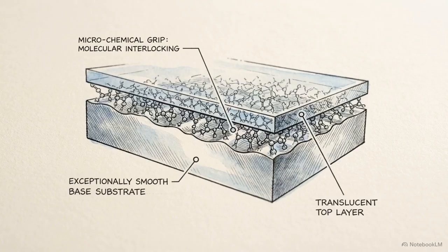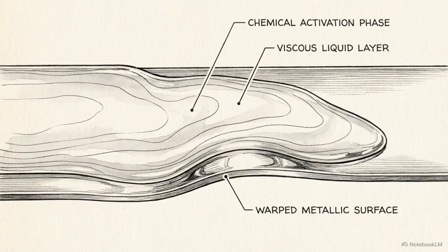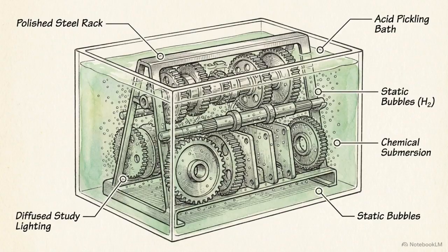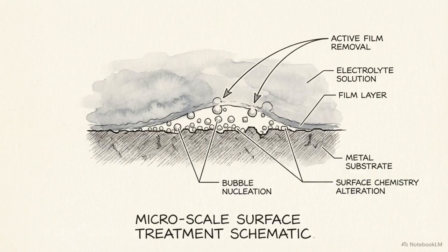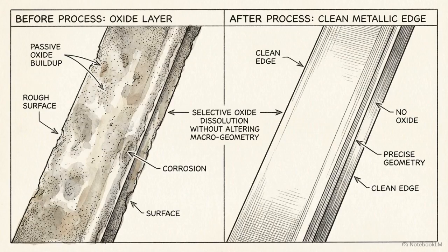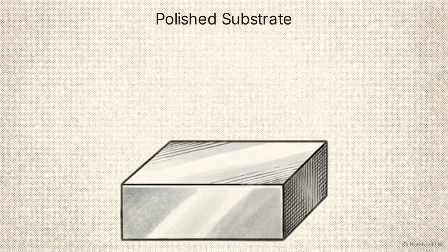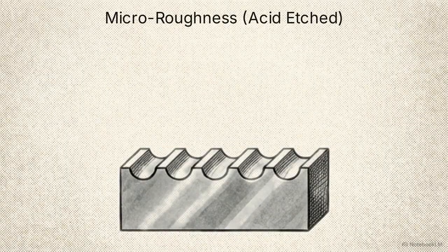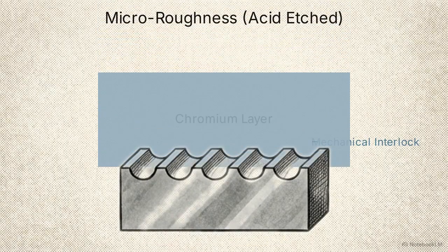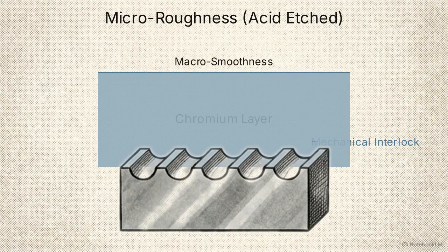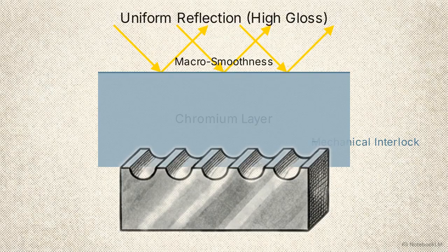To get both grip and gloss, the preparation must move away from physical abrasion and down to the microchemical level. The first step is chemical activation. Manufacturers use a process called acid pickling. By dipping the polished metal into a targeted solution, they can alter the surface chemistry. A carefully timed acid dip dissolves unwanted passive oxide layers without altering the overall macrogeometry of the polished part. The acid mildly etches the substrate, creating a controlled topography known as micro-roughness. This provides just enough mechanical interlock for the chromium to grip, but is shallow enough that it doesn't disrupt the macro-smoothness required to reflect light uniformly.